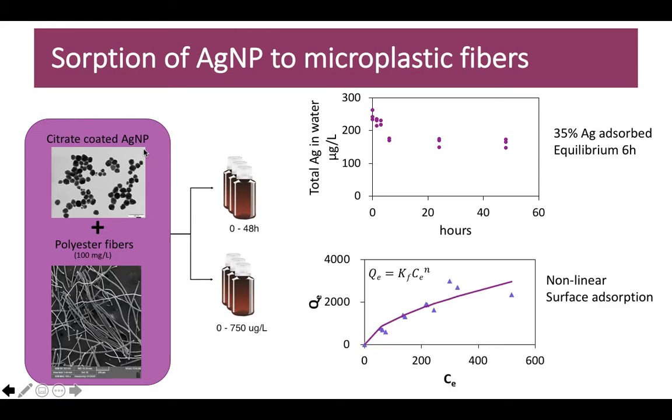Then we conducted a second experiment where we changed the concentration of the nanoparticles in the water, and we found that the quantity of the nanoparticles adsorbed to the microplastic was non-linear with this concentration. Therefore, it indicates that surface adsorption was the main mechanism.